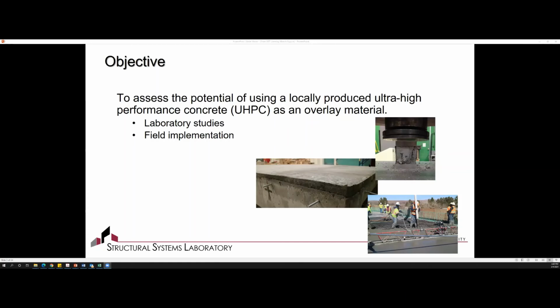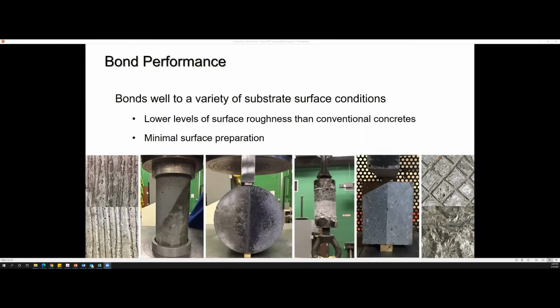Starting with the laboratory studies, we went through a lot of different tests to get to the point where we felt comfortable implementing it in the field. We started with looking at bond. We did several different bond tests to verify our behavior there. We looked at slant shear tests, splitting tension, and direct tension tests. What we found was that the UHPC bonded very well to the substrate surface conditions. We also looked at a lot of different surface textures and how those textures affected the behavior. We found that, really with minimal surface preparation, we got pretty good levels of bond.